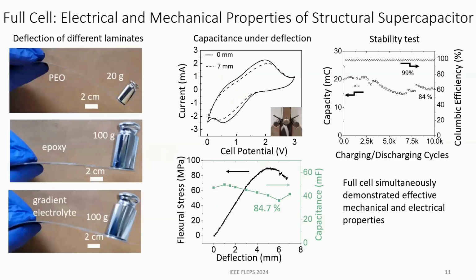So finally, here's the full cell laminated together. Here's our gradient electrolyte able to hold up 100 grams, and it still has that high conductivity of 0.4 millisiemens per centimeter. And then here's our 3-point bend test. So its maximum deflection is 7 millimeters, and it retains 85% of its capacity. And you can see point by point, it's consistent until 3 millimeters, and then it starts decreasing to 85%, and then it breaks after 7 millimeters. And it's able to cycle for at least 10,000 cycles and retain 84% of its capacity. So now we have a final working full cell.